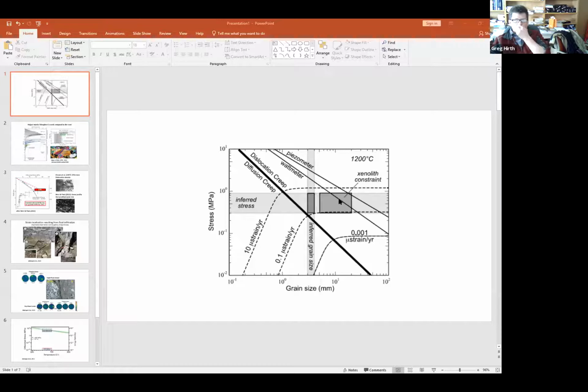Yeah, so that's really important. I mentioned briefly that seismic anisotropy is typically developed through relatively high strain deformation by dislocation creep mechanism. So the fact that Andy's model is putting us in a space where we'd expect dislocation creep to be the dominant deformation mechanism is consistent with the development of seismic anisotropy in that part of the mantle. And I'll just touch on a related aspect of the xenoliths, and then one other thing that will be a good segue into some of the stuff you would talk about, Mark. Does that make sense? Sure.